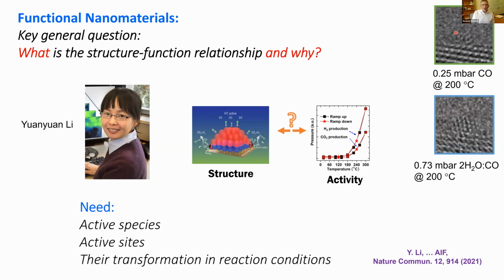But under the reaction conditions, CO spills over, converting to CO2 at the interface. So there is really no such disorder under reaction conditions. That's why you see much more ordered images.